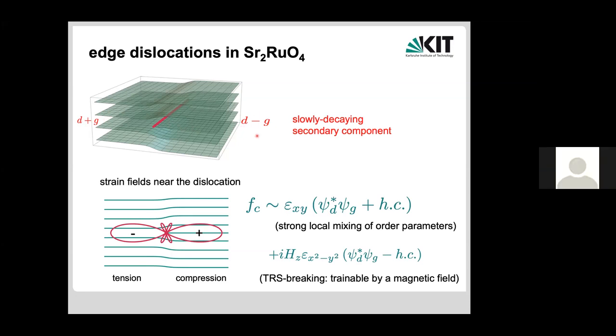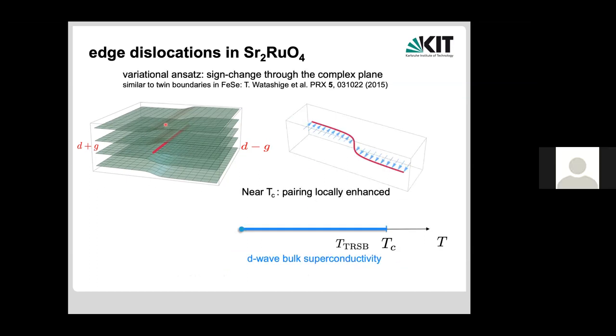Right, but then you would need to assume that far away from this dislocation, this epsilon xy would die off, right? Otherwise, it dies off only as 1 over R. So it dies off very slowly. Okay. So then if I take a contour going from positive to negative without penetrating this dislocation, then this relative sign, one component should go to 0 in between? If I take a contour going from the D plus G side to the D minus G side without going directly through the dislocation, would you expect one of the components to continuously go through 0?